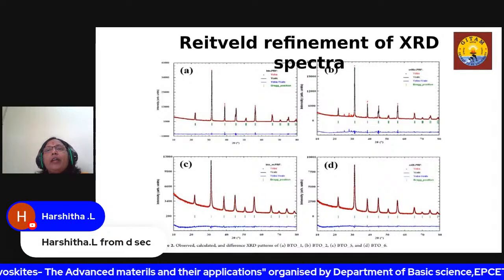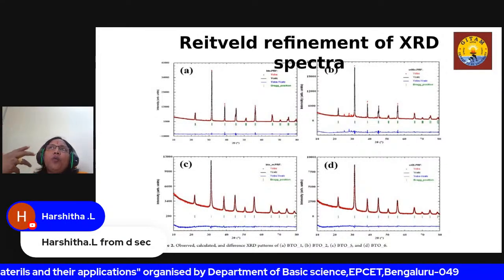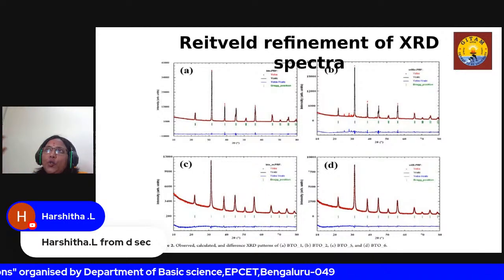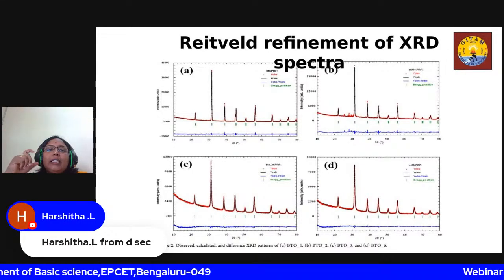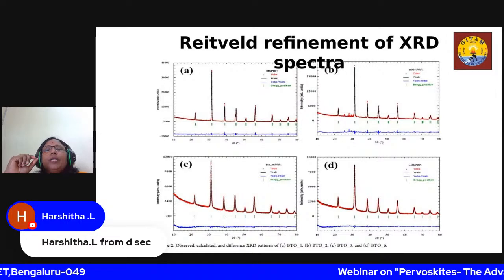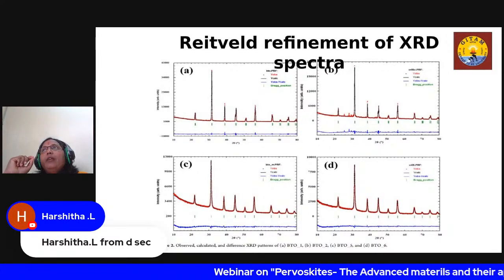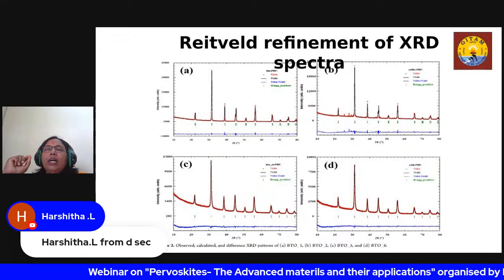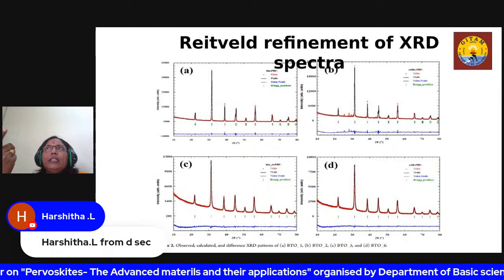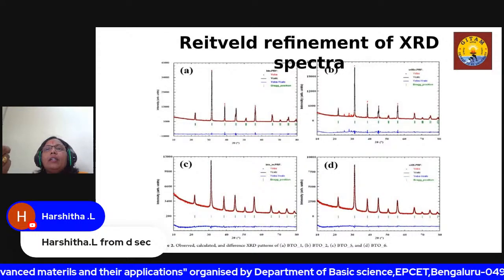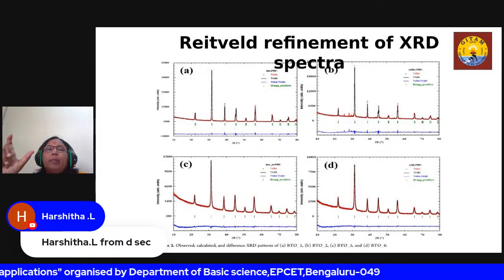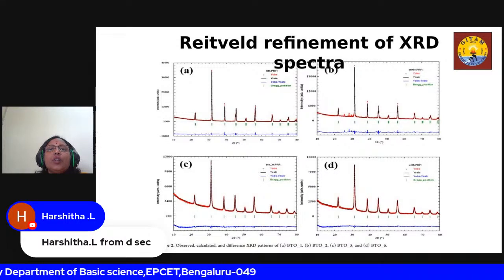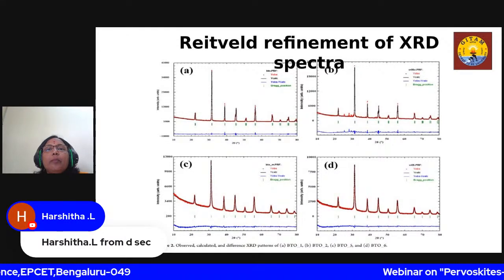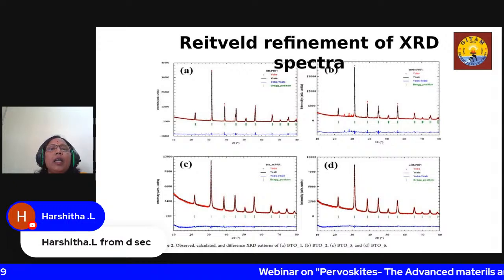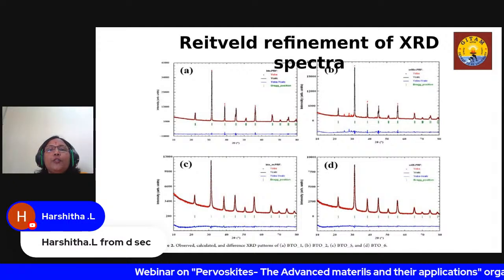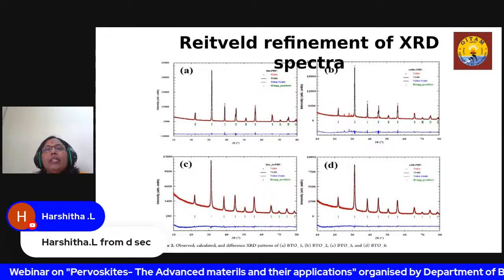And these are the Rietveld refinement of XRD. So how do we know that whatever we have confirmed via XRD is really true, or can we confirm this via theoretical analysis? Yes, we can do that. That method is called Rietveld refinement, described by Hugo Rietveld, through which we can calculate the theoretical XRD pattern, which should match our experimental pattern. So here the results you can see. The red is observed and the black is the calculated. The difference between the calculated and the experimental spectrum should be 0. Then only it reveals a nice fit.